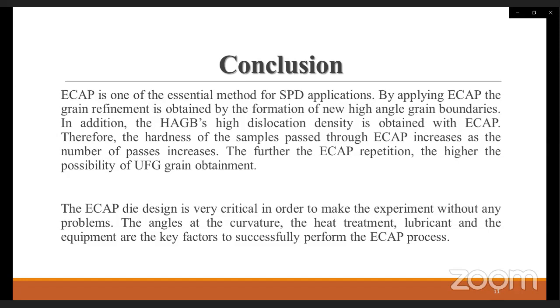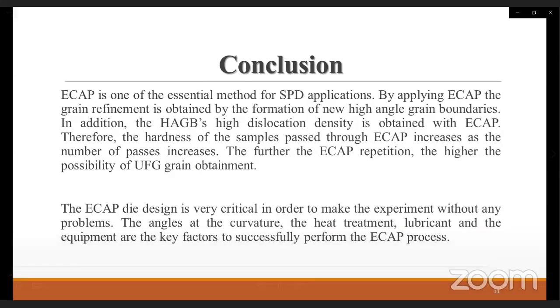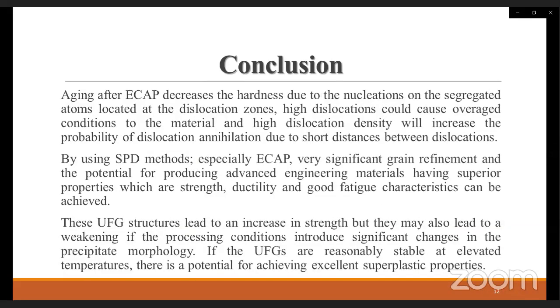The ECAP die design is very critical in order to make the experiment without any problems. The angles at the curvature, the heat treatment, lubricant, and the equipment are the key factors to successfully perform the ECAP process. Aging after ECAP decreases the hardness due to the nucleations on the segregated atoms located at the dislocation zones. High dislocations could cause overaged conditions to the material, and high dislocation density will increase the probability of dislocation annihilation due to the short distances between dislocations.